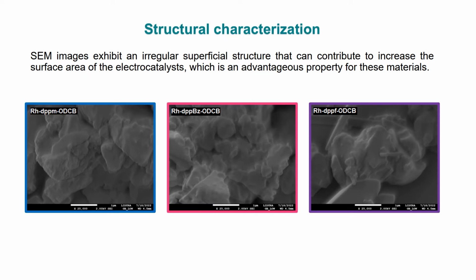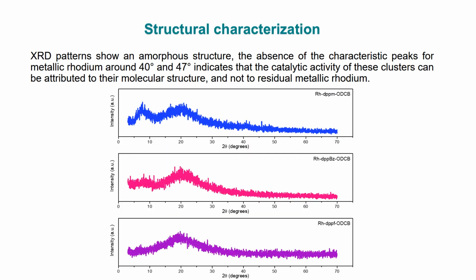Scanning electron microscopy images exhibit an irregular superficial structure that can contribute to increase the surface area of the electrocatalysts, which is an advantageous property for these materials. X-ray diffraction patterns show an amorphous structure. The absence of the characteristic peaks for metallic rhodium around 40 degrees and 47 degrees indicates that the catalytic activity of these clusters can be attributed to their molecular structure, and not to residual metallic rhodium.